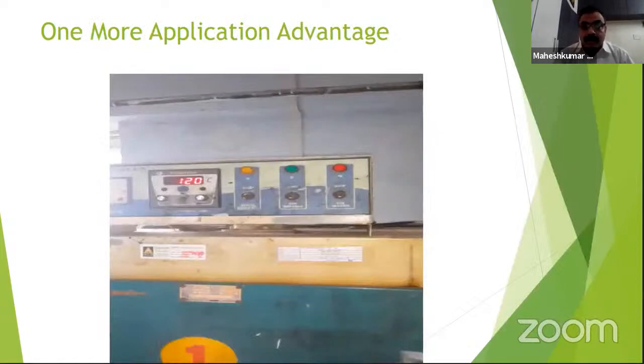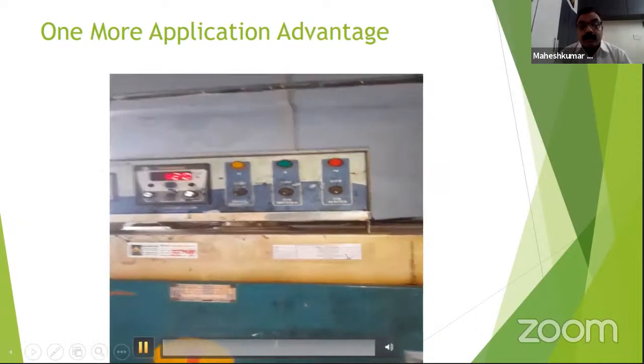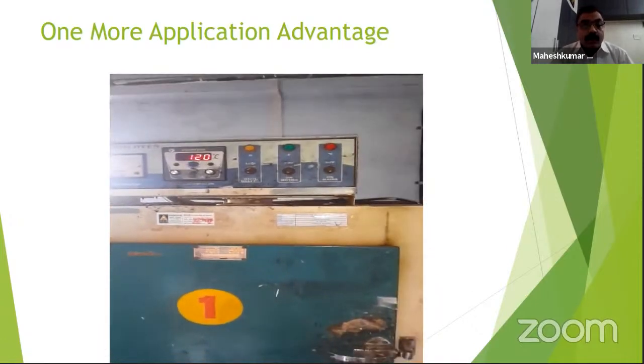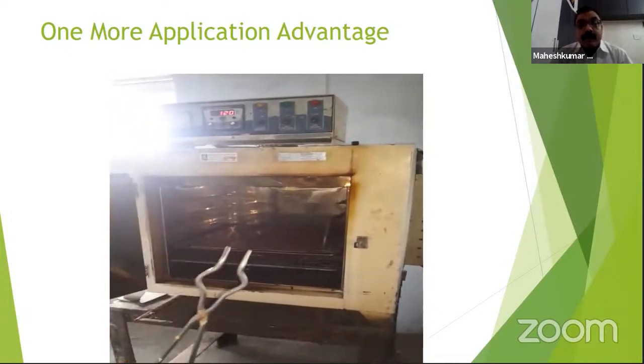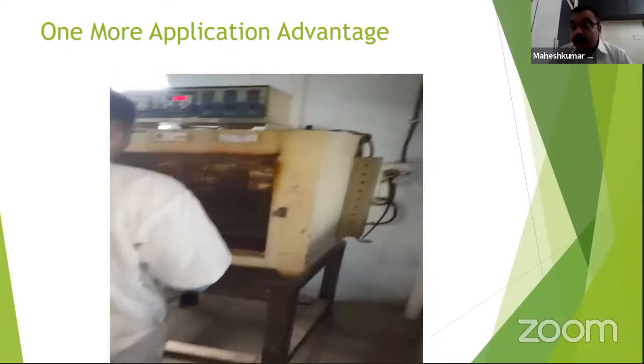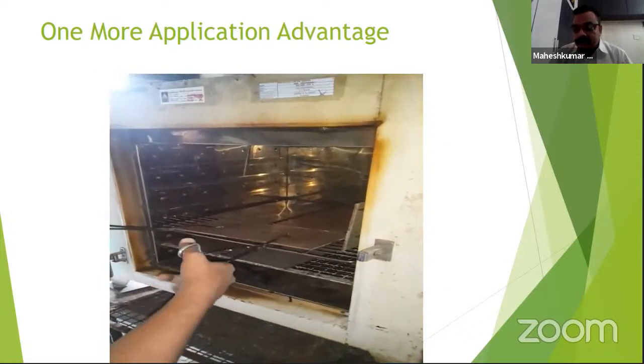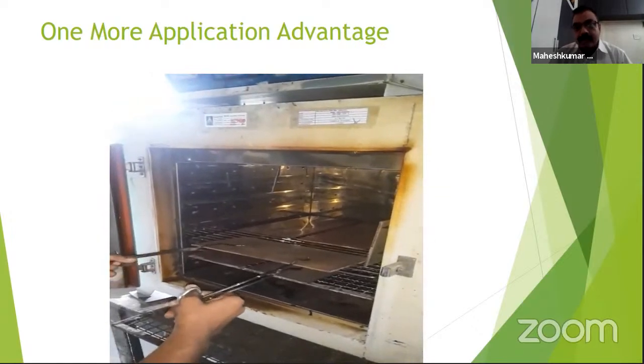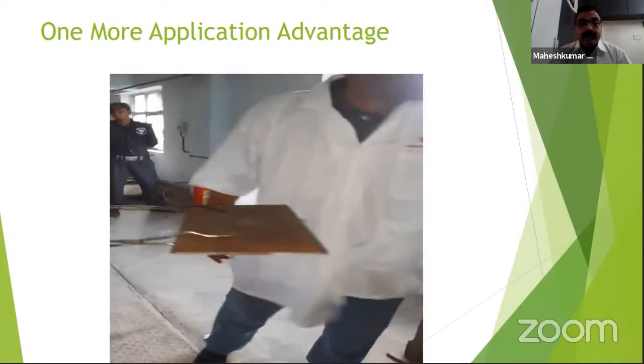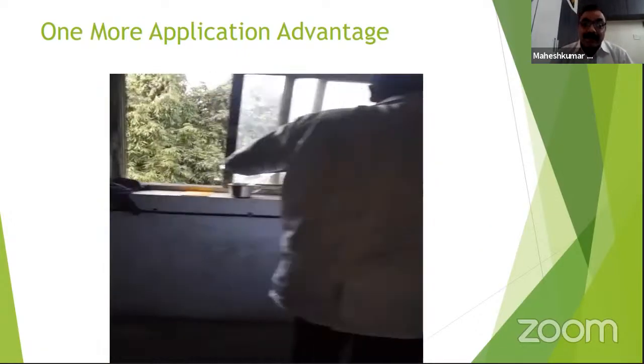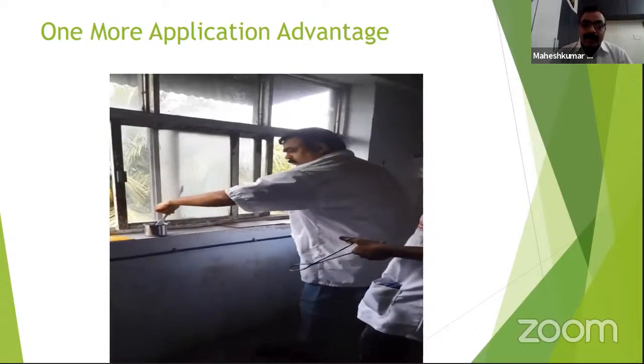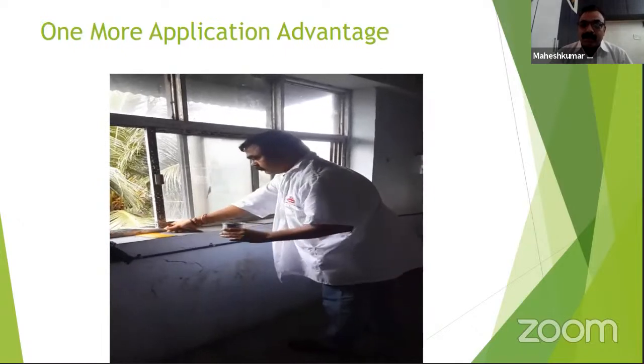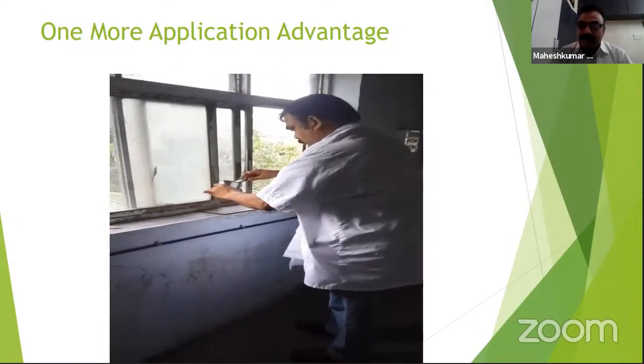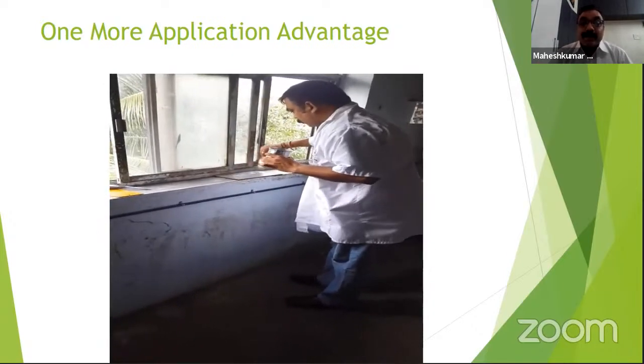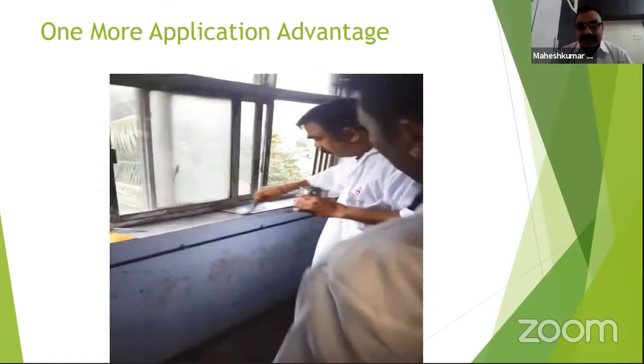Now I want to show you one video, which is going to give you a clear idea. At 120 degrees centigrade, we have kept a corroded panel without any kind of surface treatment other than ST2, ST3. Then we took it out. You can see the safety precautions that we had taken. And at that hot temperature, I took a chance without any PPE to apply the coating onto the hot surface.